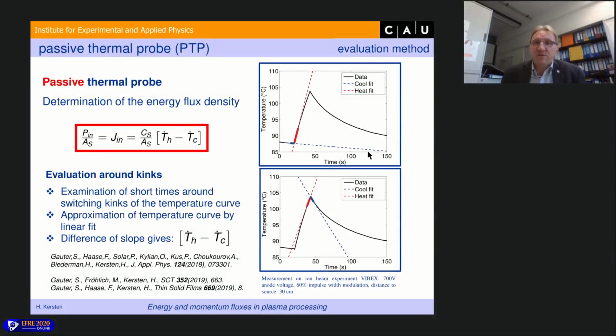And here we have different evaluation methods. We have a software and hardware to make the measurements automatically from the beginning. And usually we evaluate the so-called heating kinks here when the heating starts, and here the cooling kinks when the cooling starts, which can be measured automatically. And then the power per area can be determined. And at the end, we get a value like 5 watt per square centimeter, but this, I remind you, is an integral energy influx, which is the sum of all these